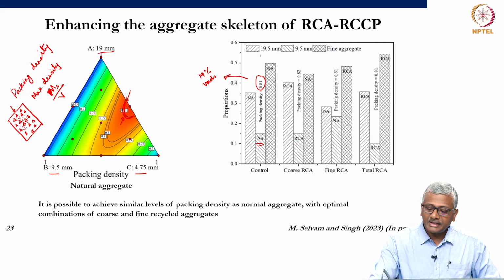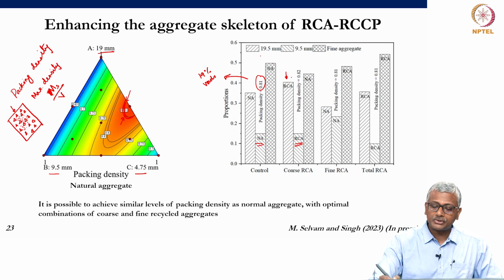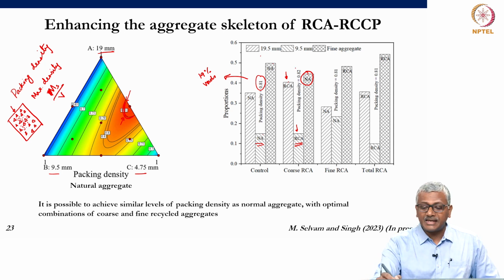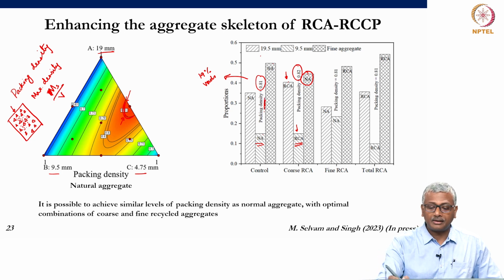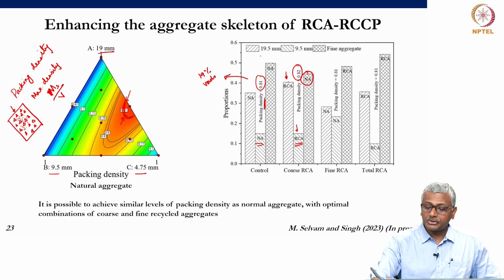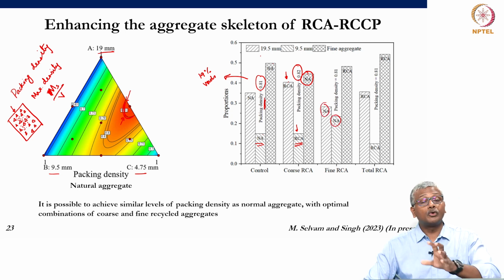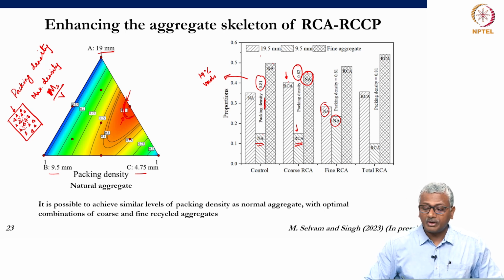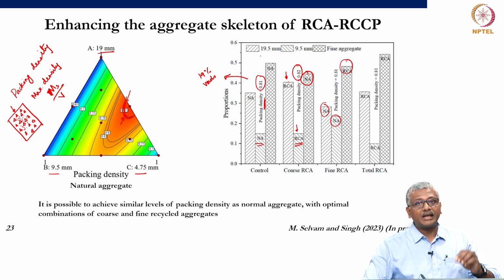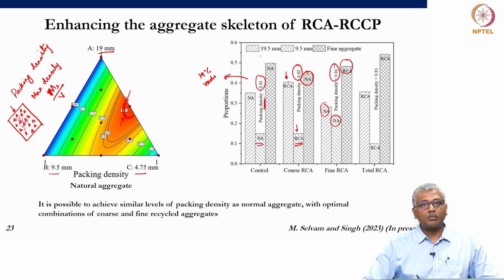So, now when you have recycled concrete aggregate of different proportions, for instance, here only recycled coarse aggregate was used, okay, of two different sizes of 19 mm and 9.5 mm. You can see that for 40% 19 mm aggregate and 15% recycled concrete aggregate of 9.5 mm and natural fine aggregate at 45%, they are able to get now the same or even better packing density as compared to natural aggregate, okay. Similarly, for proportions of normal coarse aggregate at 30% and about 25% in the case of coarse aggregate and about 50% of the recycled fine aggregate, you are now able to get the same packing density as the normal aggregate.